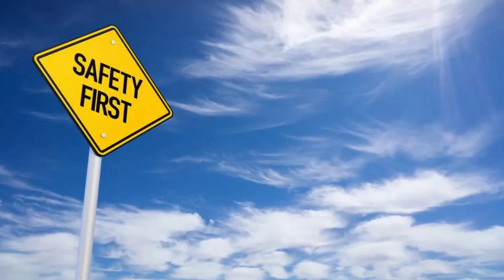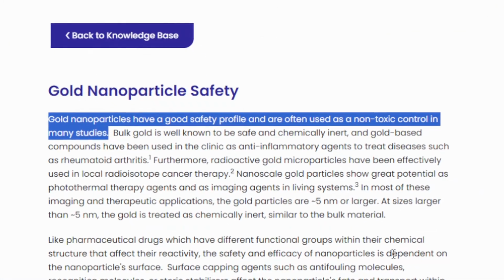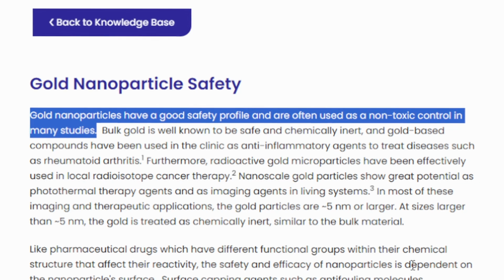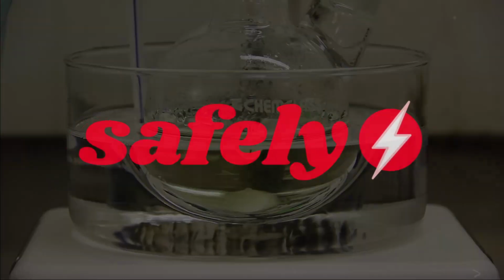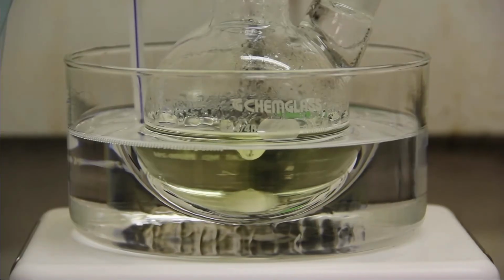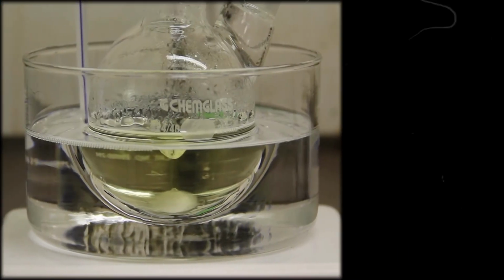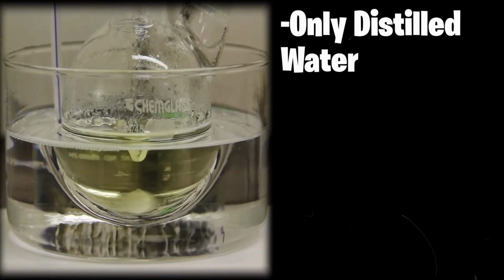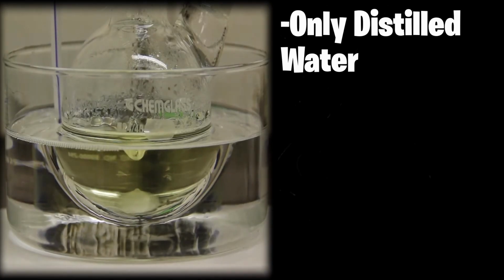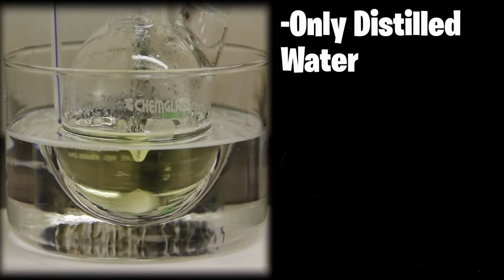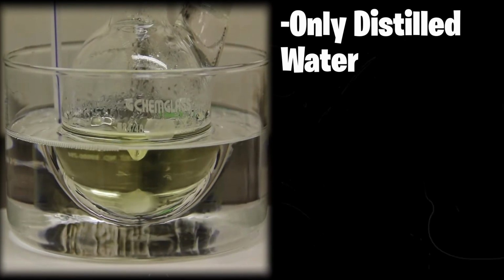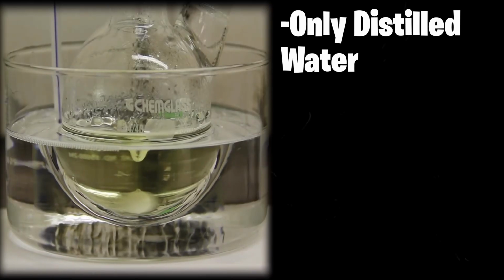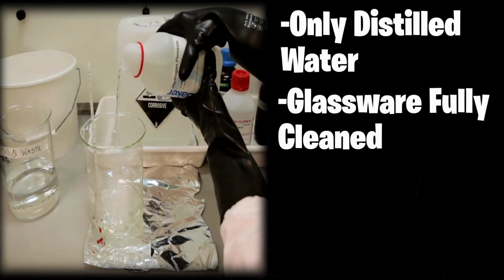Colloidal gold nanoparticles are generally known for their safe uses and relative non-toxicity towards living organisms. However, colloidal gold nanoparticles must be prepared safely to minimize potential harm when used in applications. The preparation calls for using distilled water, which should be distilled twice or even thrice, since colloidal gold is very reactive, so even the tiniest bit of minerals in water can set off massive reactions. The glassware used should be cleaned by undergoing acid passivation and thoroughly rinsed with distilled water.